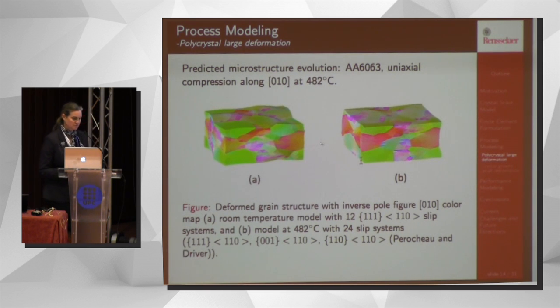So what's interesting is at this temperature, you not only have the 12 octahedral slip systems active, but it's been observed that you see slip also on the cube slip systems and on these 45-degree slip systems. Perocheau and Driver did some very nice experimental work. So if we model it with just the 12 slip systems, which would correspond with like a room temperature deformation, we see a behavior like this. We're seeing more breaking up of the grains. You can also see greater heterogeneity in the deformation.